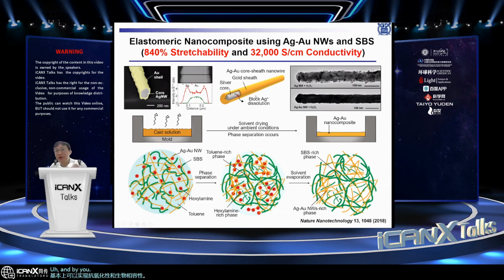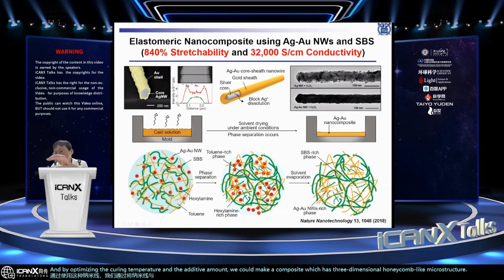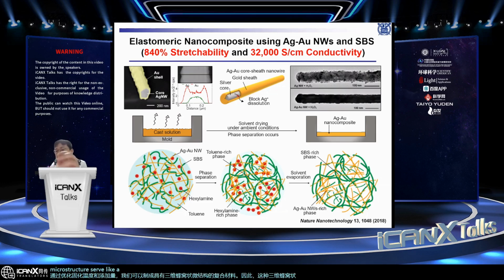And by using this nanowire, we made a stretchable elastomeric nanocomposite by mixing nanowires with SBS. And by optimizing the curing temperature and the additive amount, we could make a composite which has a three-dimensional honeycomb-like microstructure. So this three-dimensional honeycomb-like microstructure serves like a spring. So it has a mechanical microstructure, so the stretchability can be enhanced more. So by using this nanocomposite, we can achieve 840% stretchability and 32,000 siemens per centimeter conductivity.